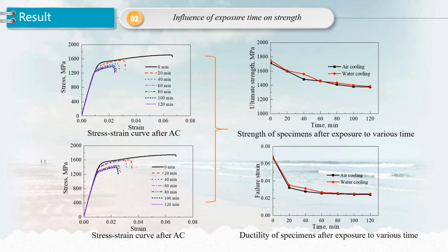Since the fire accident lasted more than an hour, in order to investigate the influence of heating duration on the mechanical properties of steel wire, tests were conducted on steel wire heated to 500 degrees centigrade with different exposure time. It is seen that strength and ductility decreased with increasing exposure time, and specimens exhibit more loss in ductility than strength in the heating process.